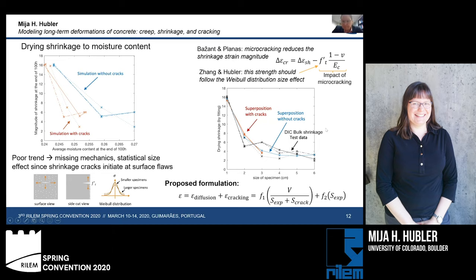And here what we've done is we've superimposed the results of our diffusion models using the X-ray data on top of DIC measurements, or digital image correlation measurements. We have taken a bulk shrinkage cement test.